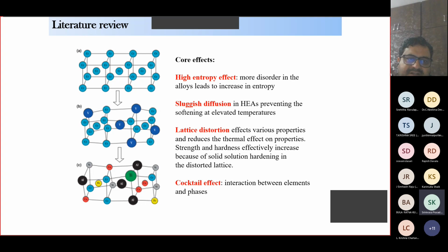And the four possible effects that come out of these cocktails, the mixing at atomic scale, are the high entropy effect because of the disorder that they bring at atomic scale, and sluggish diffusion. To form any new material, diffusion is very important, which is mass transport at atomic scale. And because of the presence of a wide variety of materials whose melting points are different, whose densities are different, whose diffusivities are different, either at room temperature or high temperatures, you expect that you form some kind of an amorphous structure, but that's not the case. And also because of the variation of the atomic radii of the participating elements, you also expect some kind of distortion in the whole lattice, contributing to the high hardness. For that, the original attributes of different elements, you put them together, they also get intermixed, and you bring some kind of a cumulative effect, which is called the cocktail effect.